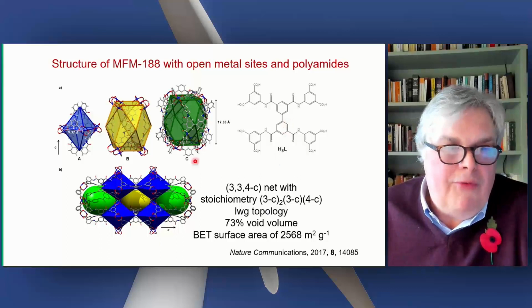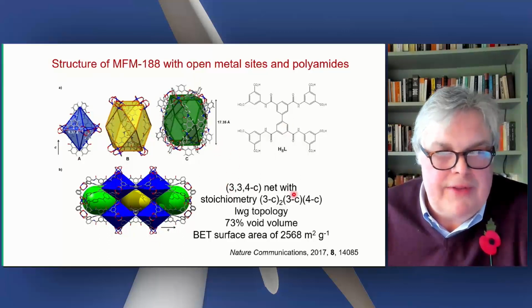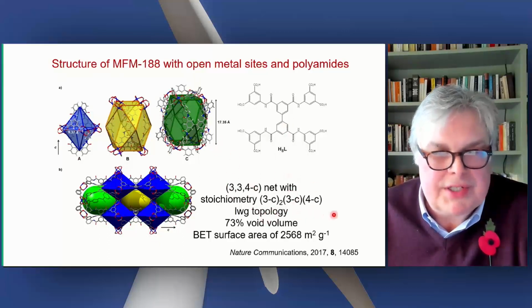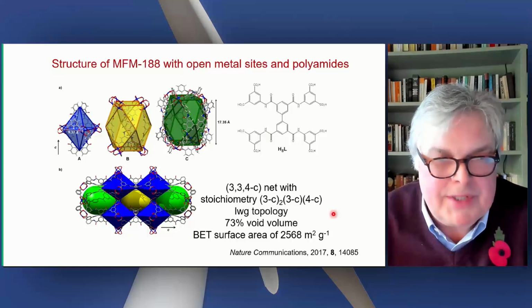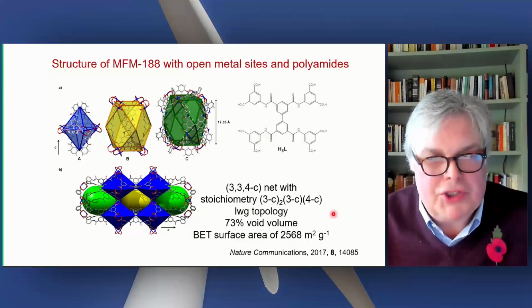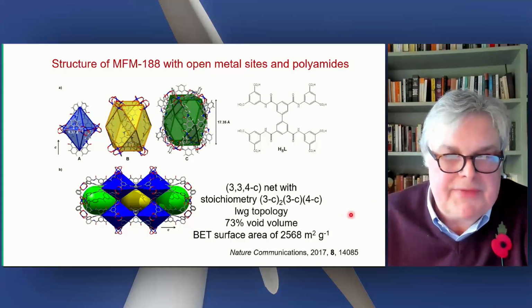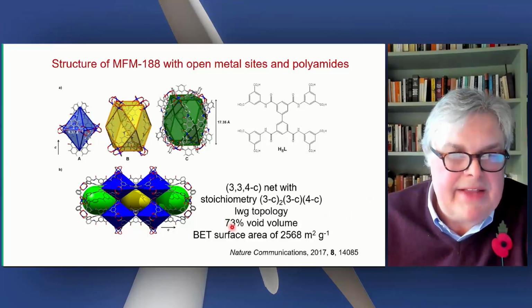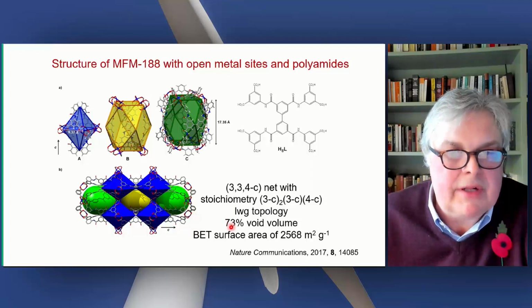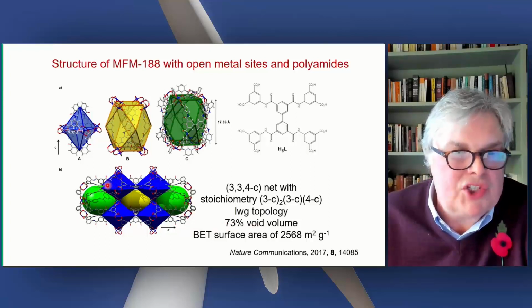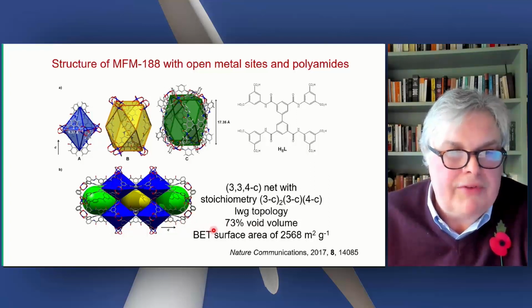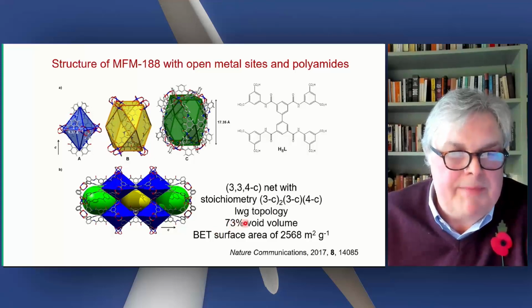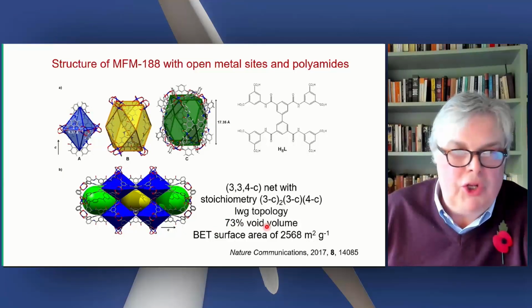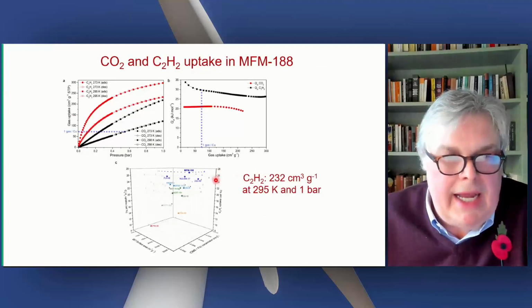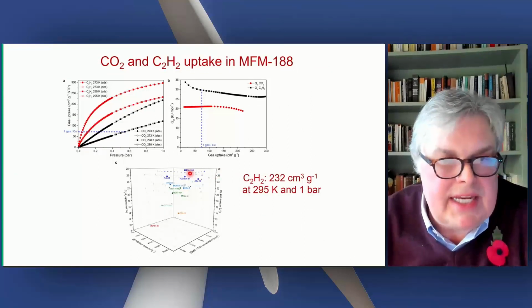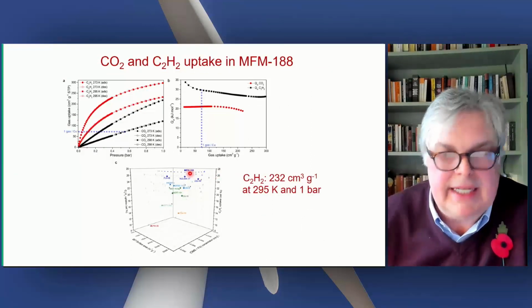with copper 2 forms a very unusual structure. This is the nomenclature of these structures. There's a whole area of MOF chemistry defining this type of topological analysis. I won't go through this for obvious reasons. Suffice to say that this is a very porous material. 73% of its structure, once you remove the solvent within the pores, has void volume. I just highlight here acetylene uptake. So this has a very high acetylene uptake.